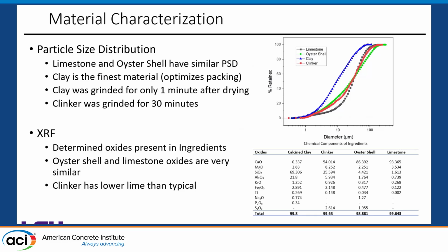Furthermore, for material characterization, we did a particle size distribution using a laser diffraction method, and then also XRF to determine the oxides present. For the particle size distribution, we found that the limestone and oyster shell had relatively similar sizes, which does bode well for good substitution. And then one thing that was truly interesting was that the clay was seen to be much finer, which could optimize packing in blends that use the clay.